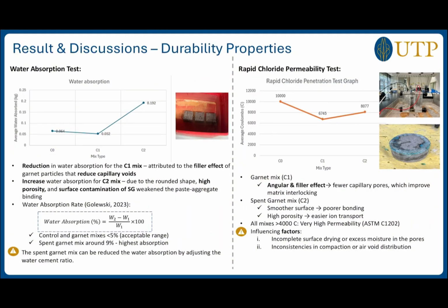So for durability properties, we have the water absorption test and the rapid chloride permeability test. For the water absorption test, we can see the garnet mix has reduced water absorption compared to control because it is attributed to the filler effect of garnet particles that reduce capillary voids. And the spent garnet mix has the highest water absorption due to the rounded shape, high porosity, and surface contamination of spent garnet that can weaken the paste aggregate binding.